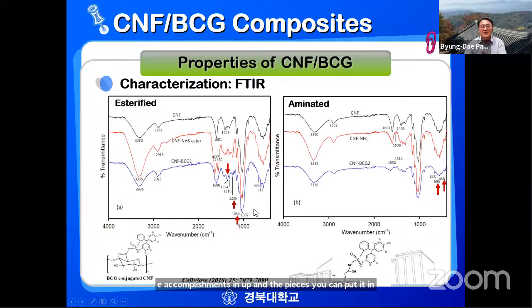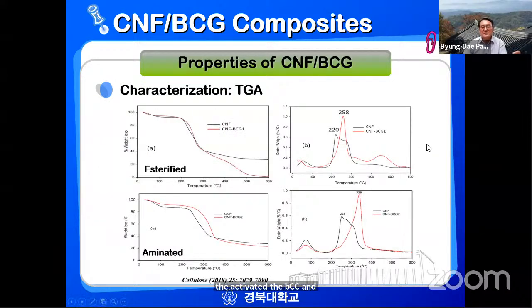That means that the CNF and surface-modified CNF have reacted with the activated BCG, and also the aminated one has new peaks for the CNF BCG. That means the amino groups reacted with the succinimidyl group of the activated BCG. And also with the TGA, it changed a little bit: for esterified and aminated CNF the degradation temperature increased. That also indicated the activated BCG has reacted on the surface-modified CNF.